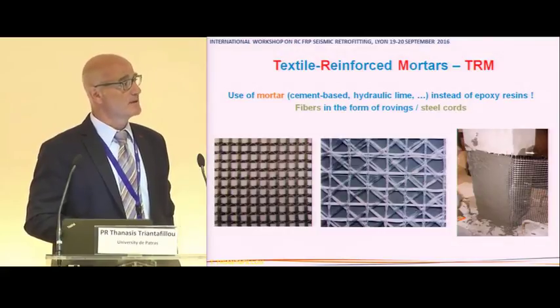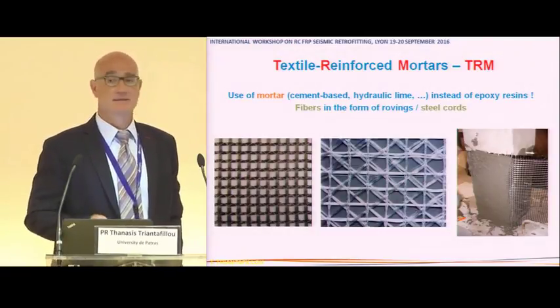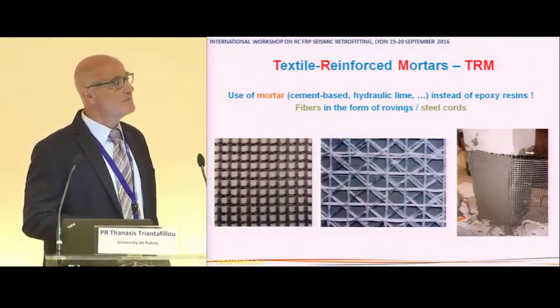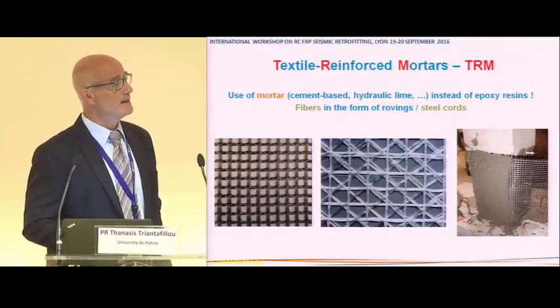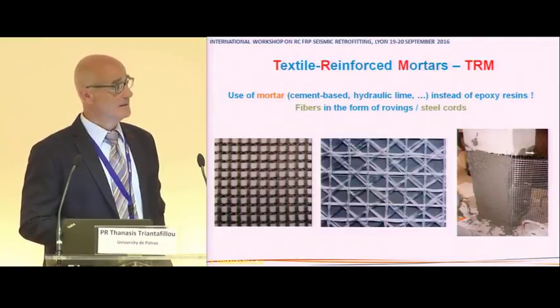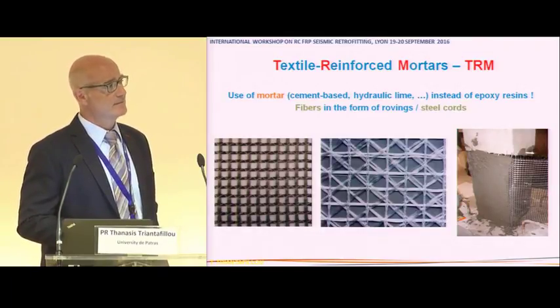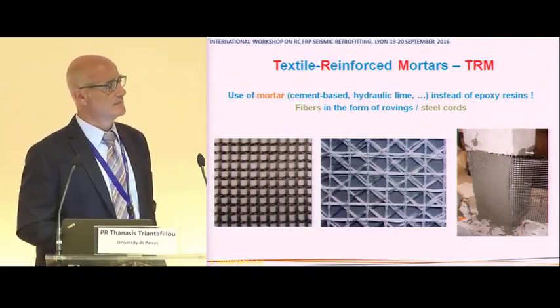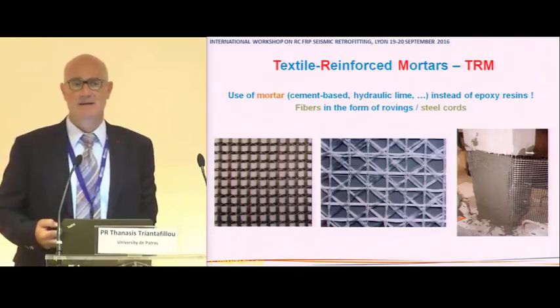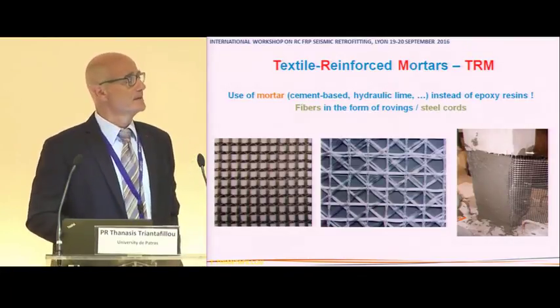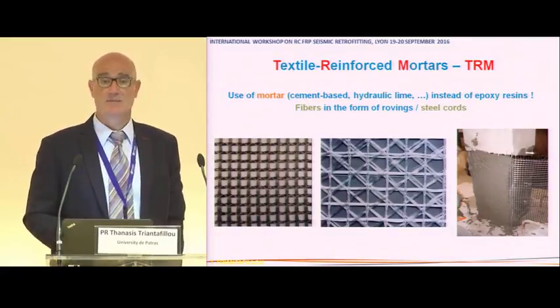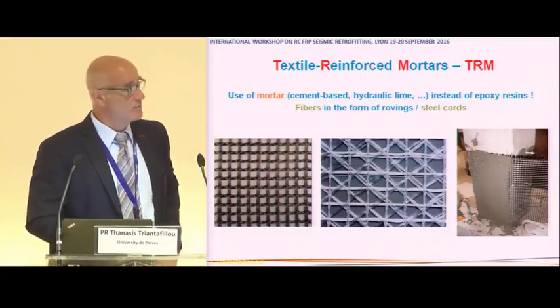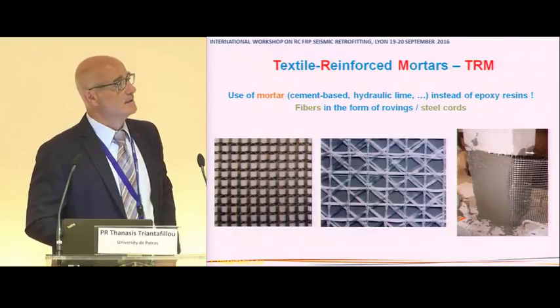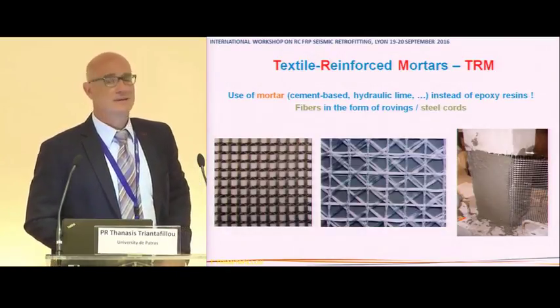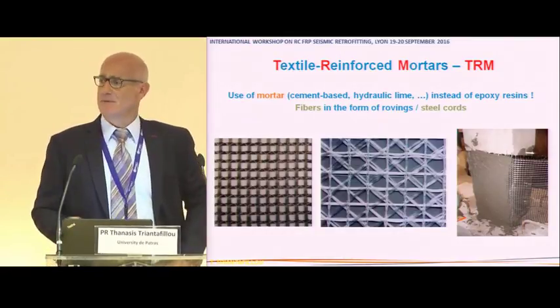So for a number of reasons, we thought that replacing epoxies with more user-friendly mortars, green or non-green mortars, cement-based or maybe hydraulic lime-based materials combined with fibers, including steel cords, fibers in at least a couple of different directions, that is combined with a textile type of structure. Those materials can create a composite system that does not suffer from all the disadvantages associated with epoxy resins. That's what we call a textile-reinforced mortar, as opposed to FRP, TRM. There are many names in the international literature. TRC in Germany, textile-reinforced concrete. FRCM in the States, etc., etc.